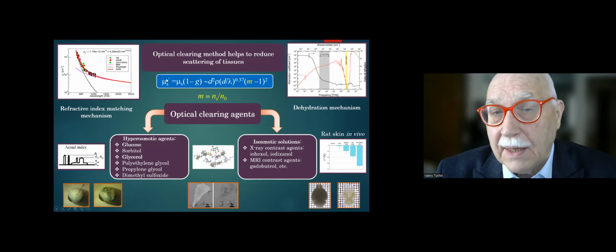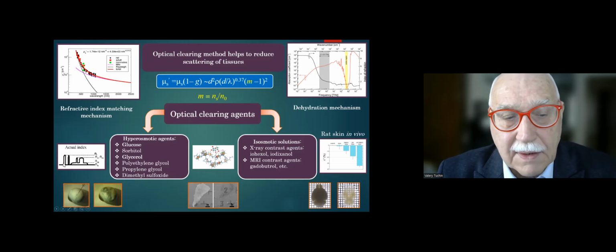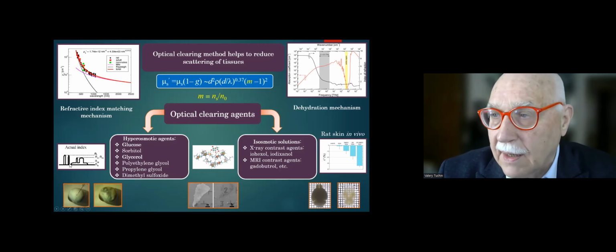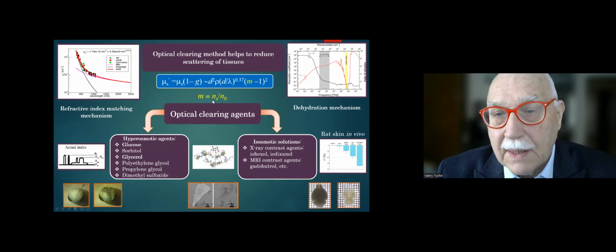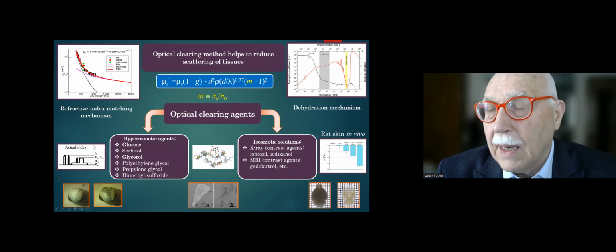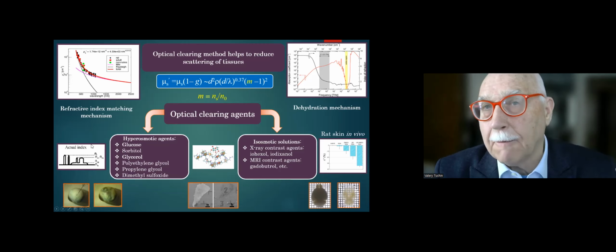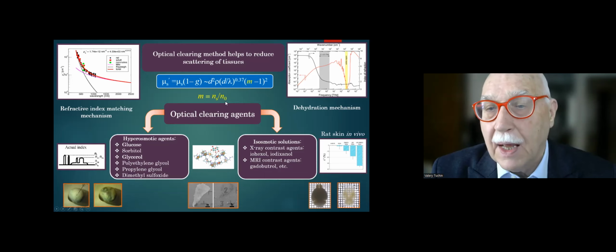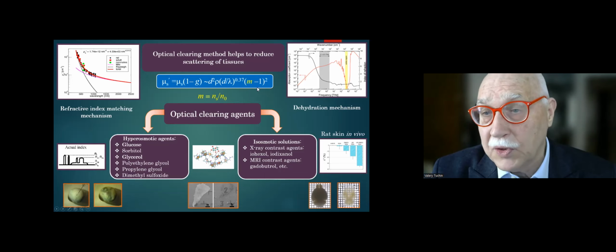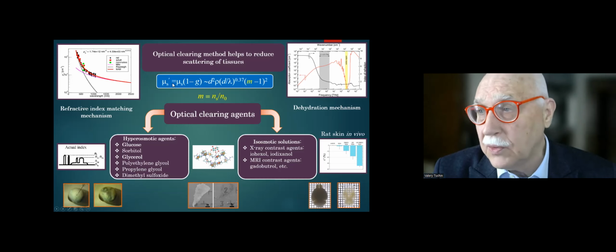And this scattering parameter depends on the refractive index mismatch of the scatterers, like parts of the cells, like the nucleus, like other organelles. And if we equalize the refractive index of the background, the interstitial fluid around the scatterers, like fibers or, as I said, mitochondria and other organelles, we can reduce scattering significantly, because it's squared, you see here, and therefore we can make tissue or any scattering media more transparent.